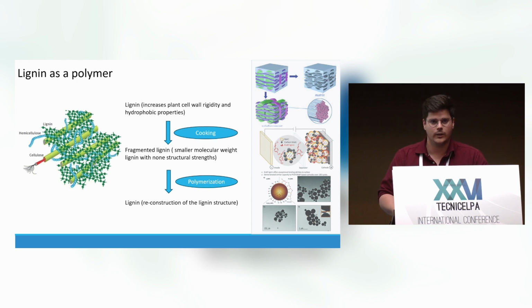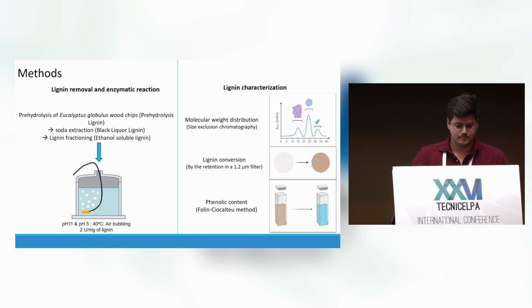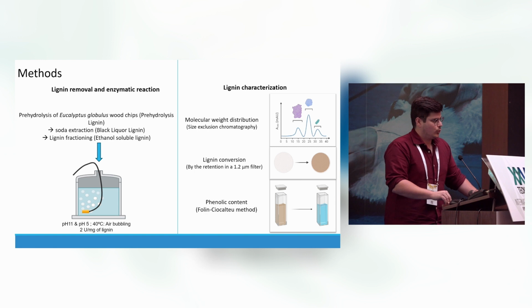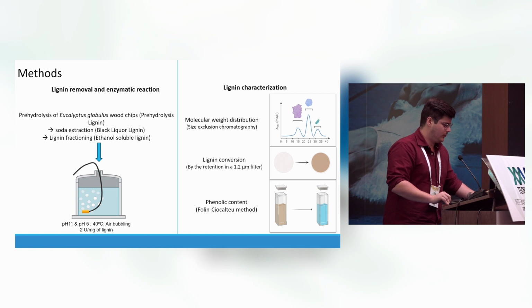So we have lignin, we dissolve it and we fragment it, and then we need to repolymerize it to achieve this function. For this means, the method that we applied, based also on my PhD project, we studied the PREHYDROLYSIS, in this case of soda cooking of Eucalyptus globulus wood chips. We did the PREHYDROLYSIS to achieve a lignin with fewer contaminants, like the sugars from the hemicellulose. As I mentioned before, the soda extraction will allow us to work with the lignin with better characteristics for the aim of this work.